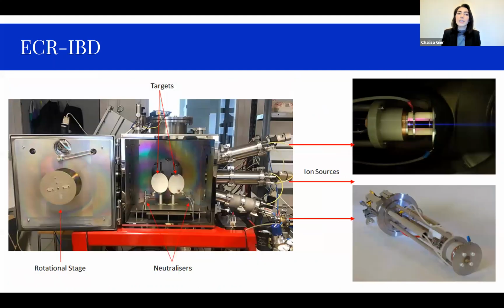Here is the second ECR ion beam deposition system that we have, which is basically a scaled up version of the previous system. This system has 6 ion sources with 3 ion sources on either side of the chamber. We've added a rotational stage to the system to create a more uniform coating, and because it's a larger system, it's easier for us to create mixed material coatings compared to the smaller system as well. And this is what the sources look like when you take it outside the chamber.